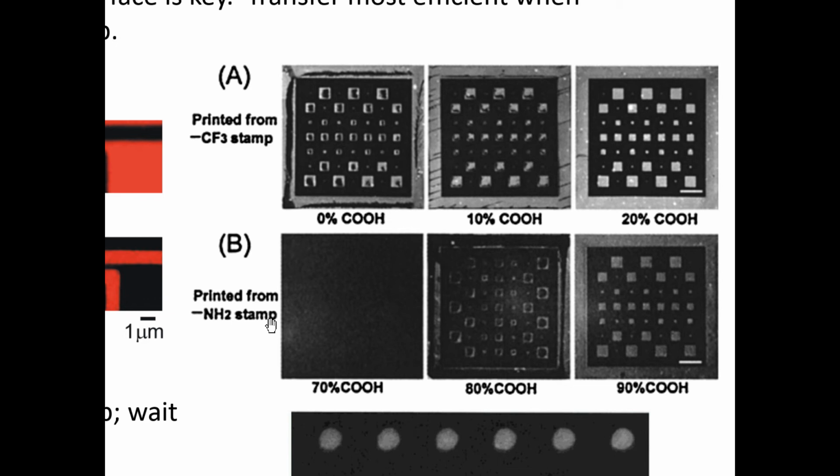Yeah, you can do corona treatments on PDMS to make it more hydrophilic. So, for example, if you were working with a solution and you were having a lot of trouble getting that solution on the stamp, then you do a little bit of corona treatment to it. So there's a little bit of empirical play here that you have to do. You just know what the techniques are.